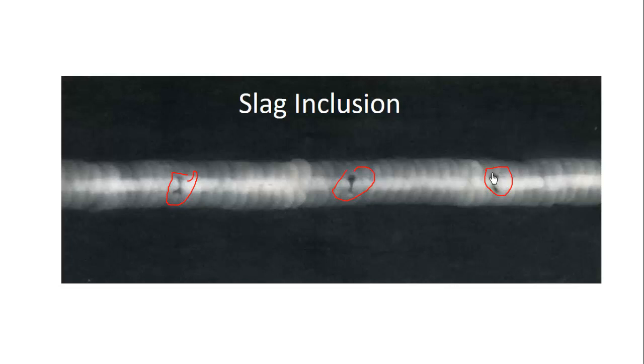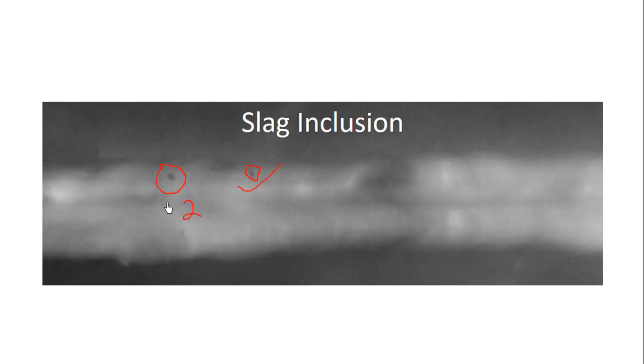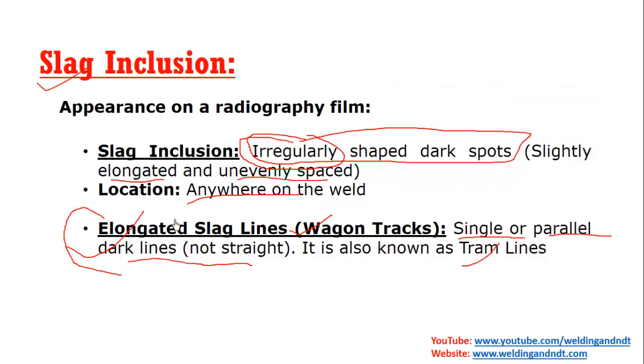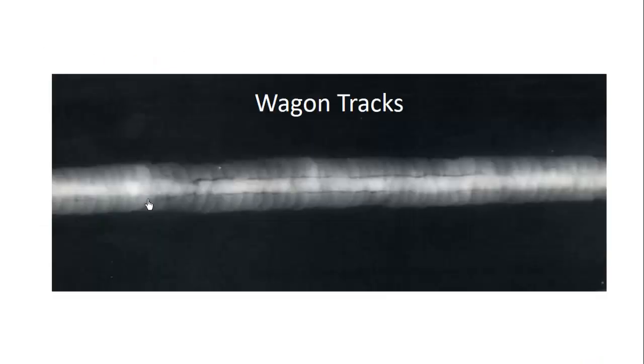In this picture you can see irregular shaped dark spots — this is a slag inclusion. Friends, my question number two: what defect is this — is it a slag inclusion or porosity? If you have forgotten, please watch Part 1 where I explained how porosity looks. Now, there is one variant called wagon tracks or tram lines, which are elongated slag lines. They appear as single or parallel dark lines, but remember they will not be straight.